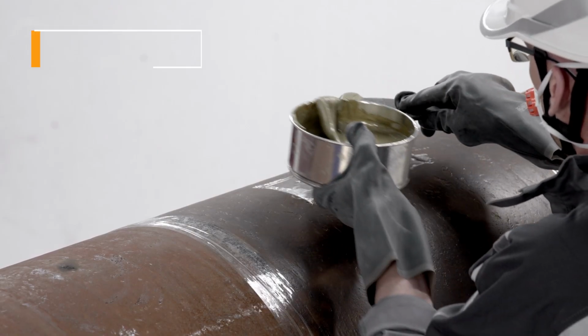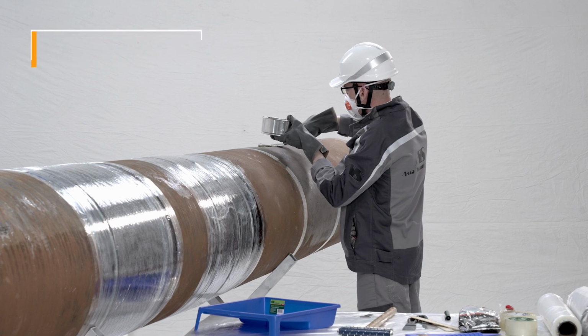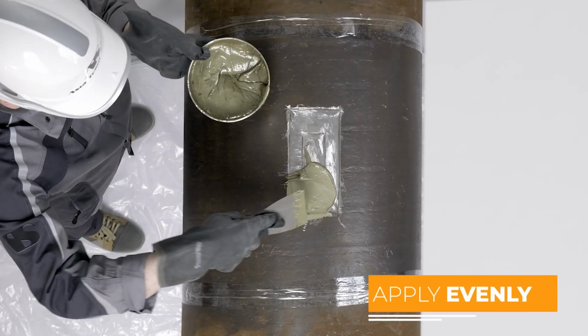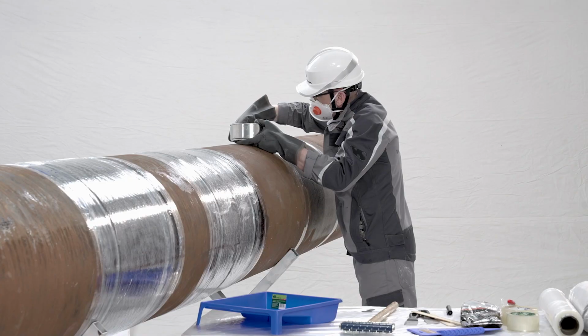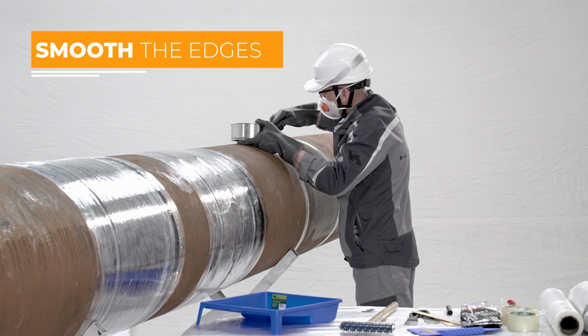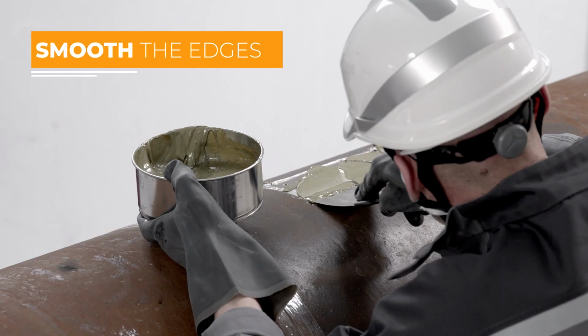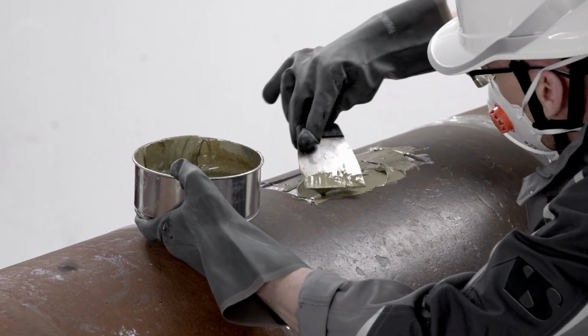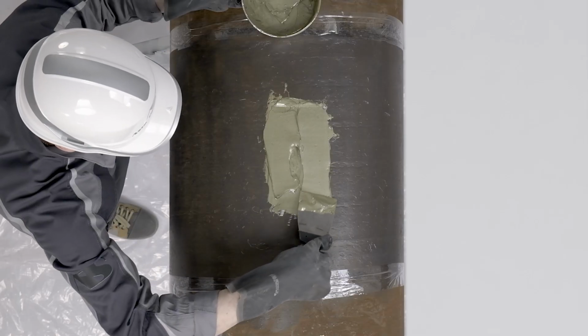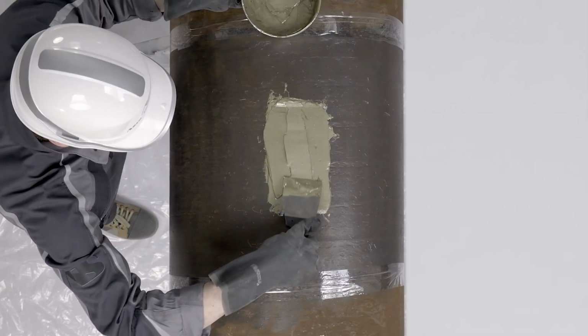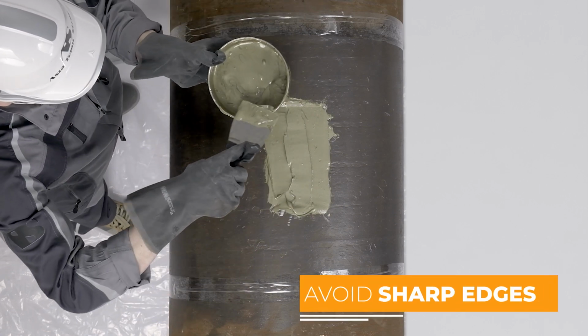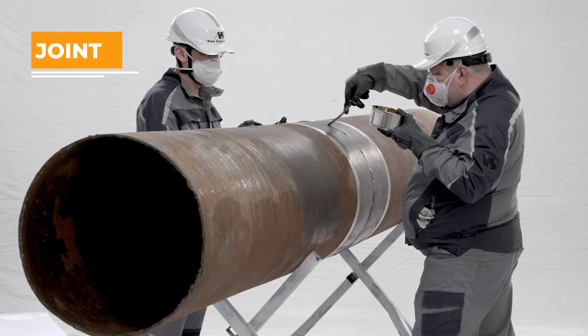Applying the paste to the loss of metal defect. Use a spatula to apply the paste evenly to all voids. The edges of the defects should be smoothed to create a smooth transition when installing the coupling. Smooth the paste so that it follows the contour of the pipe as well as possible. Avoid forming sharp edges.